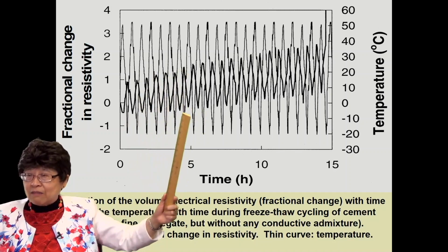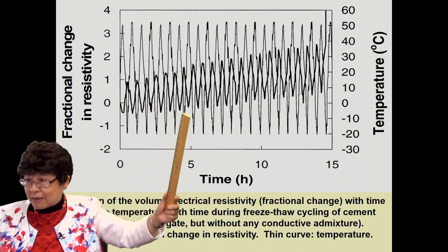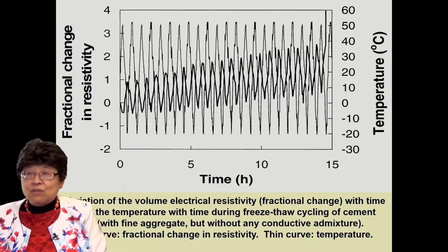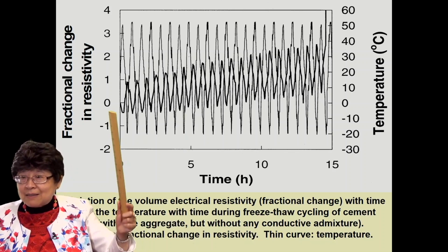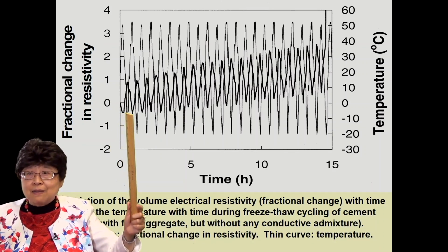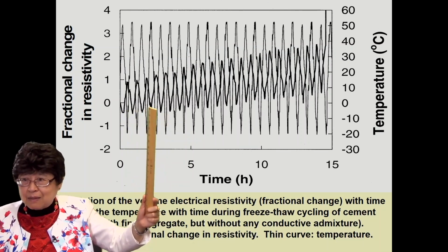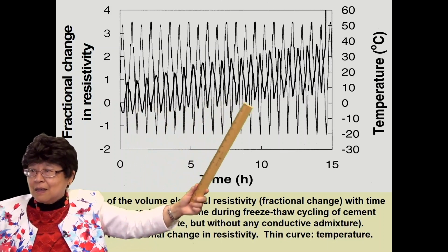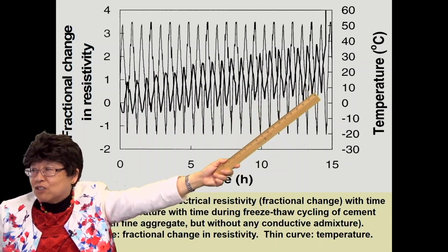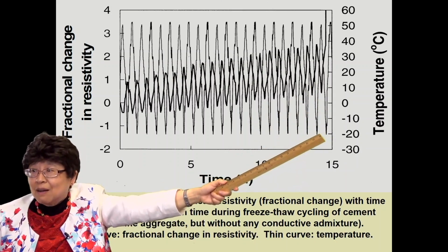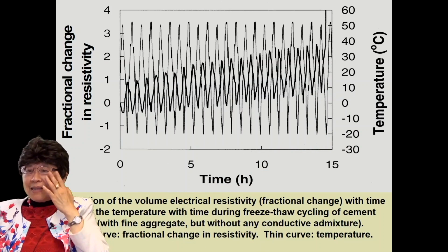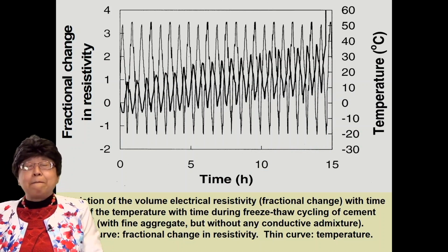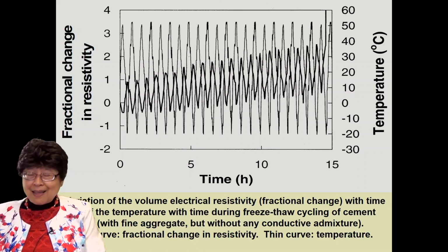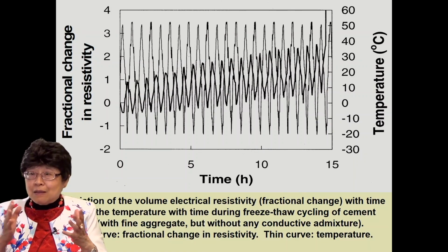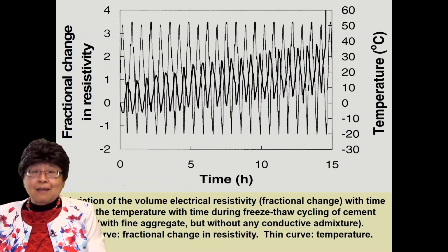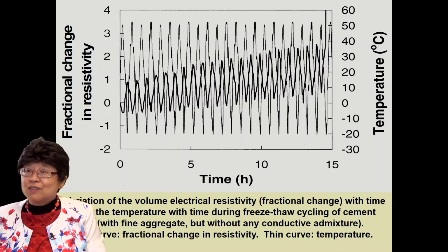both the upper envelope and the lower envelope go up. Every cycle it creeps up a little bit. Okay? And that is due to damage. And this means that damage is incrementally inflicted on the cement in every cycle. Every cycle it keeps having damage inflicted until it dies, fractures, and it fractures at the coolest point of the last cycle. Okay? And it turns out that freeze-thaw durability is a big, big topic in the field of cement. And this is the first time anyone has been able to look in real time at the process of the freeze-thaw cycling damage.